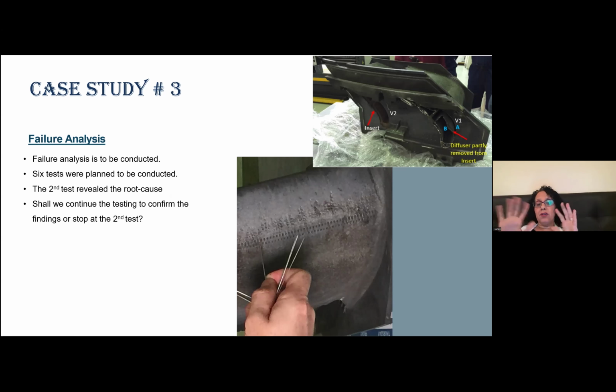For this specific failure, we planned 6 tests. We did the first test, which was macrography, and in these holes, these needle-sharp parts, we found that the holes were blocked with a powder. So we pushed the powder out, took it for XRD and analyzed it. And we found out that this powder actually came from a sealing that they use for these turbines.